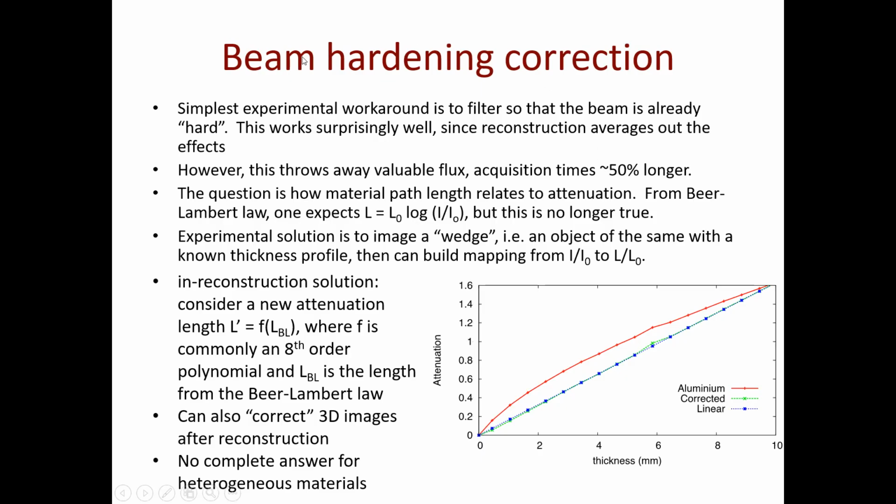So this beam hardening correction is hard to do unless you know what you're imaging. A lot of times the different X-ray facilities will do enough tests with known samples. Oh, I put a cylinder of aluminum and outside of it something else, right? And if I know what I'm imaging, I can do these corrections. With porous materials, that's a little harder. And with porous materials, it's never going to be an exact game.